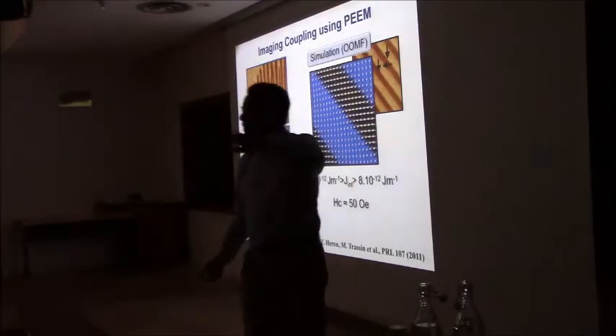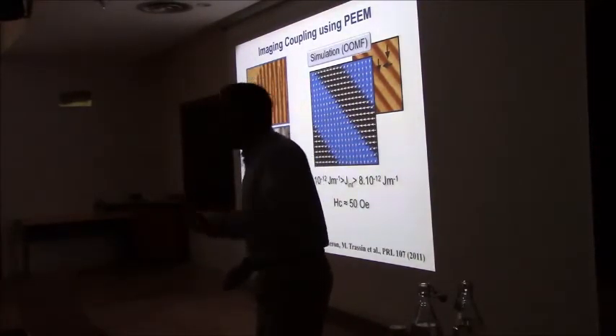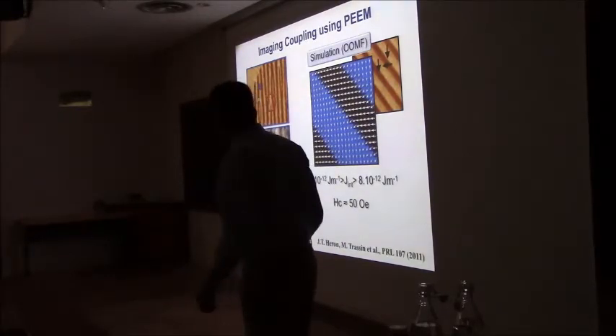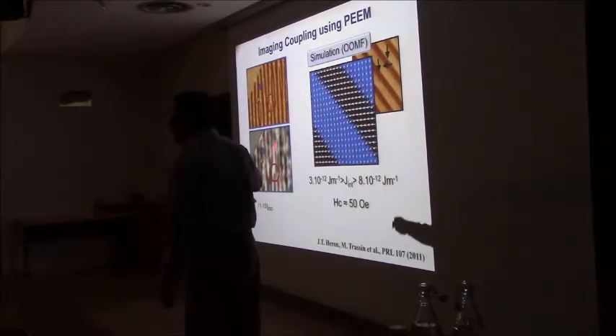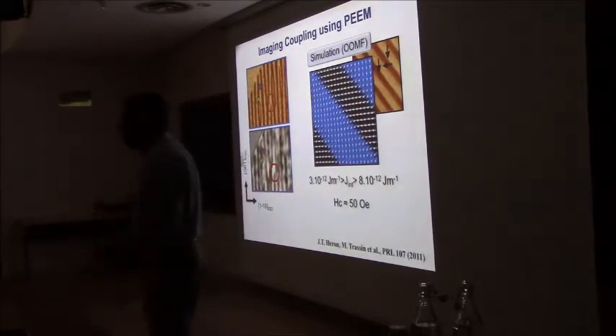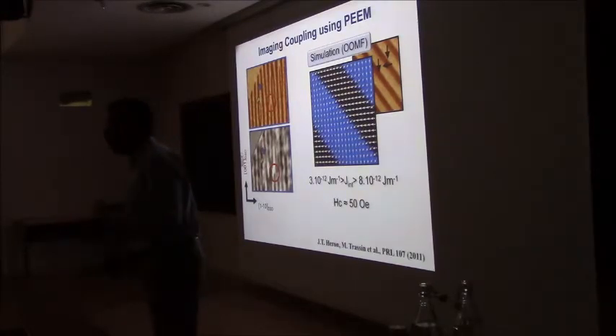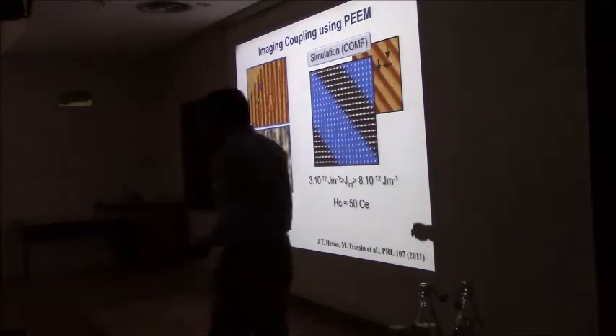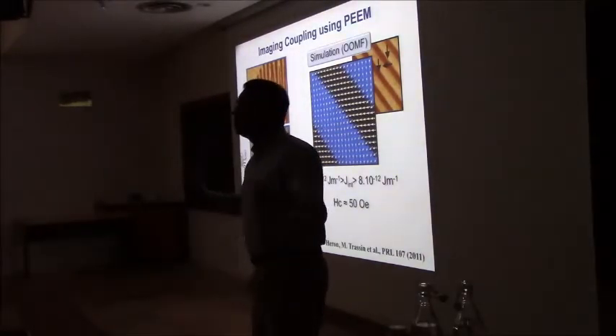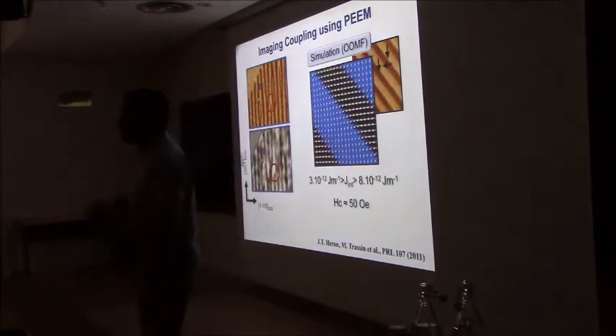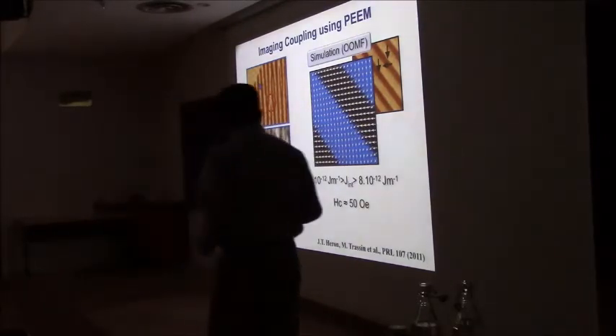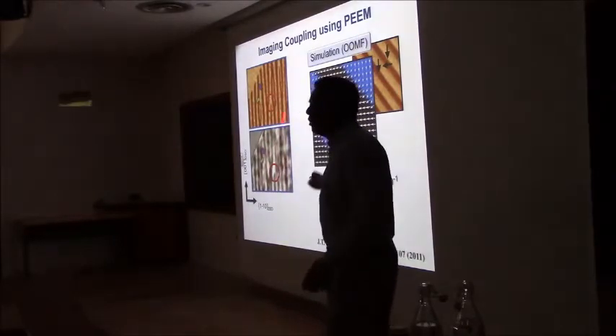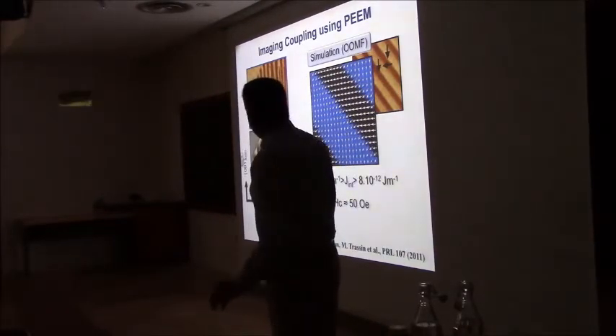I can now put a very thin layer of a ferromagnet and ask, what happens to the magnetic moments in the ferromagnet? And it turns out that this is the image of the ferromagnet captured using photoemission electron microscopy. We'll talk about this in quite a bit more detail tomorrow. We use circularly polarized X-rays. The helicity can change depending on the sample. A ferromagnet will actually give you differential absorption, and this is called X-ray magnetic circular dichroism. We'll go a little bit more into the detail tomorrow. But what we found was that the magnetic domains in the ferromagnet, the cobalt iron, mimic the ferroelectric domains.